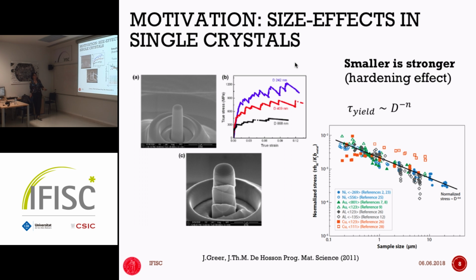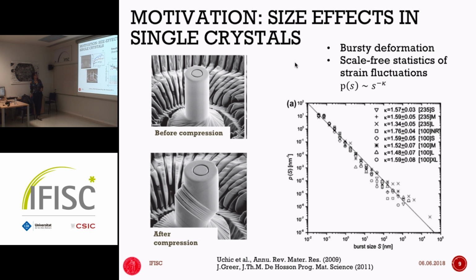So here is the experimental data collapsed onto a log-log plot to show the emergence of this power law with an exponent that we don't understand. We don't know, but it seems to be quite robust. And you can see it here in a particular example where you apply a compression on a nanopillar, and then eventually at the end of the experiment it's broken and it has shear bands. But in between, when you measure the strain and plot it in this curve, you have these strain bursts, but the yield point is increasing with decreasing diameter of the nanopillar. All right? And the strain bursts, as I said before, seem to have power law distributions with an exponent that fluctuates around 1.5. So it started with the 1.5 avalanche statistics, earthquake-like events in single crystals, but then it turned out that there is quite a bit of variation around that exponent, and we don't understand why that is. Why is there a power law? So there are a lot of open questions.